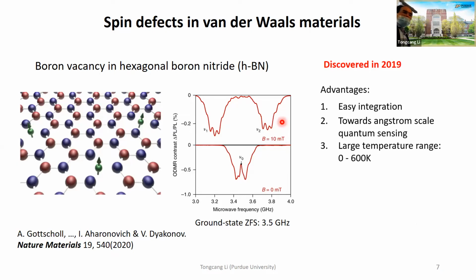So there are several advantages with the boron vacancy in 2D material. In hexagonal boron nitride, it's very easy for integration because it is a van der Waals material. So you can just peel it off and then put it where you want. It also has potential towards angstrom scale quantum sensing. And also, very importantly, it works over a very large temperature range from 0 Kelvin to 600 Kelvin.